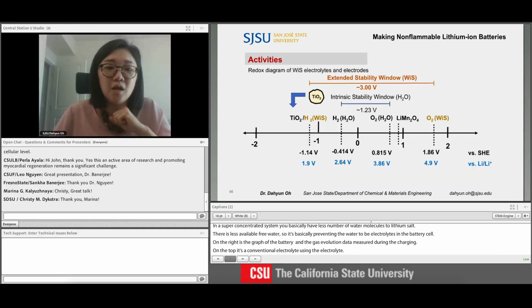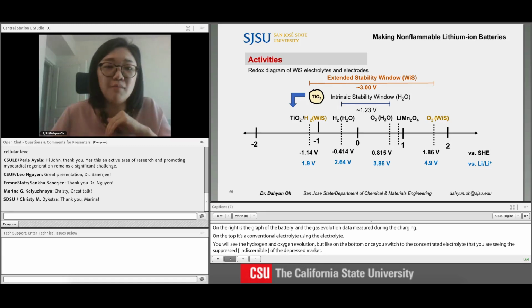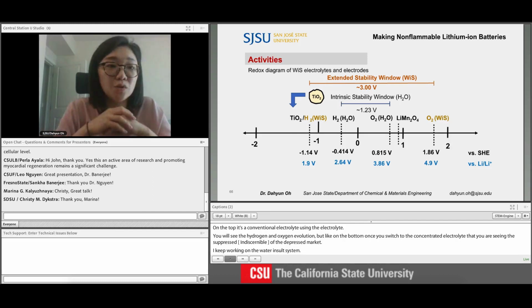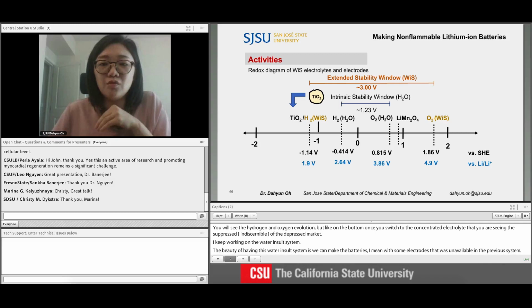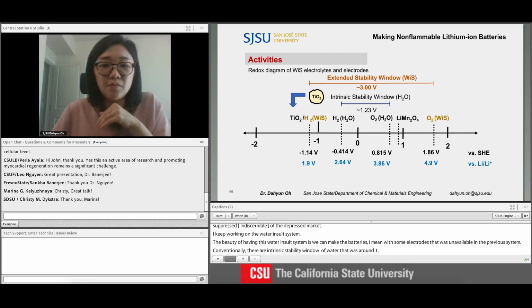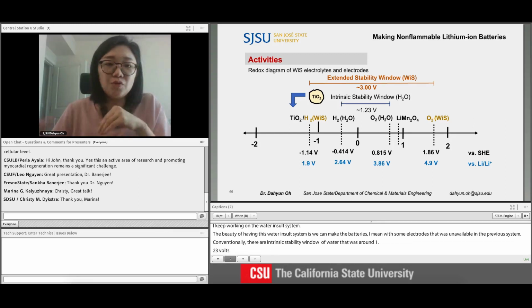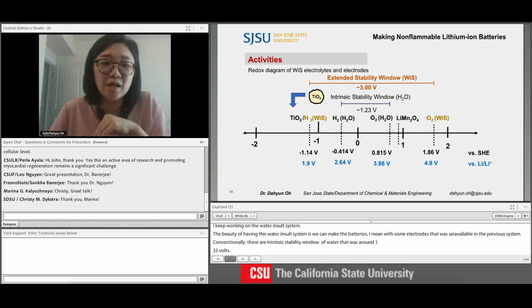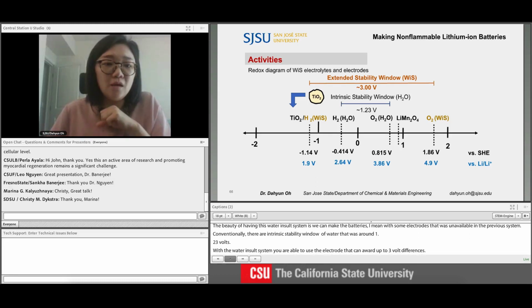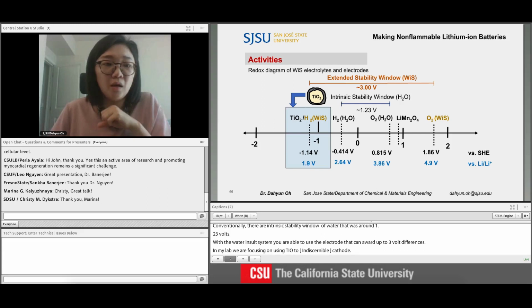So I keep working on this water-in-salt system. The beauty of having this system is that we can make batteries with electrodes that were not available in previous aqueous systems. Conventionally, the intrinsic stability window of water was around 1.23 volts, but with the water-in-salt system, you are able to use electrodes that can work up to around 3 volt differences. In my lab, we're using a TiO2 anode and a lithium manganese oxide cathode. Mainly, my research group is focusing on how we can stabilize the surface of the TiO2 anode by introducing artificial SEI layers.